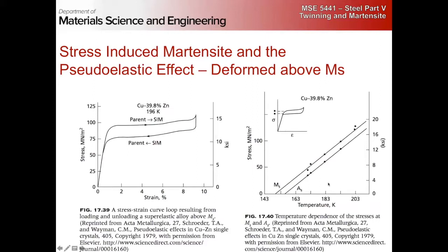For this hysteresis, right? I mean, it's just the work done during the process. You have all your inefficiencies, right? If you had a perfect single crystal and you were just transforming it there and back, your hysteresis would be very small, if measurable at all.